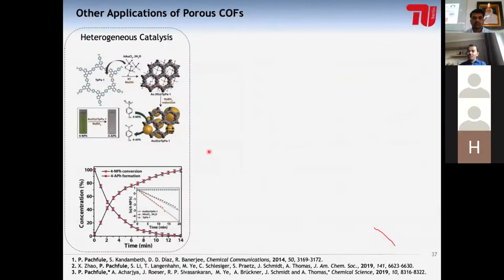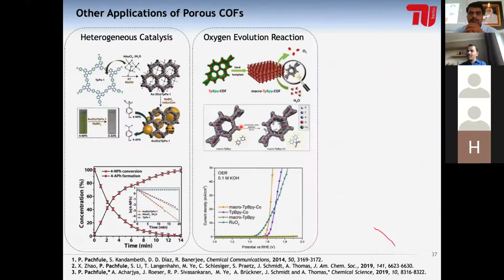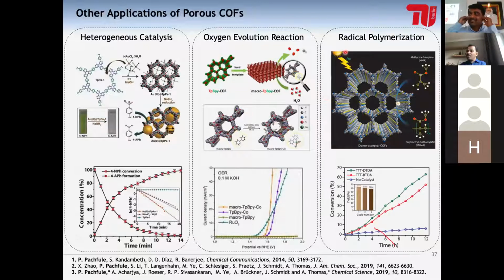Lastly, not only photocatalysis, but we have deposited some materials like metals on top of graphene on covalent organic frameworks and did some organic transformation reactions. We have also incorporated bipyridine moieties, coordinated different metals, and did the oxygen evolution reaction. And very recently, we have had a wonderful result where we showed radical polymerization using covalent organic frameworks. If someone is interested, please browse through the publications below here.